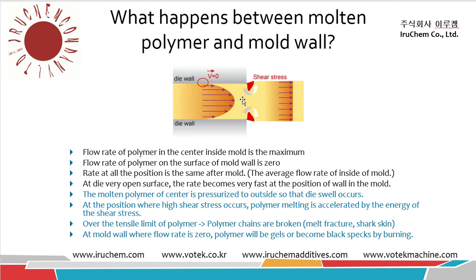Because of this reason, it produces small molecules as mentioned previously. The molecules are small, and also the big pressure contributes. Also, inside the mold, because the flow rate at the wall is zero, the heat from the outside makes the polymer burn and then gel. So lots of gel and black specks are made here, and it also becomes die drool on the outside.